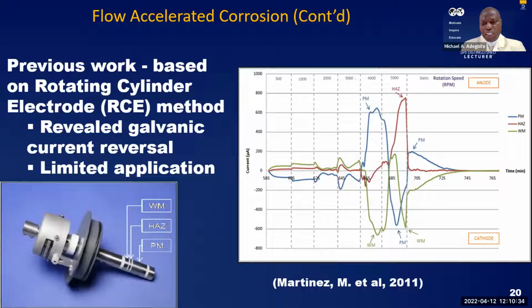In typical work that have been used to study the effect of inhibitors and to study preferential weld corrosion is this work by Martinez. Study the work, but because of the limitation of the speed or because of the limitation of the shear stress that could be generated, that could be simulated, this particular method falls short of it. But all is not just negative. A lot of lessons that we can learn from this work. And it is that it demonstrates that indeed inhibitors, chemical inhibitors, are inconsistent. They are not as efficacious as they have been assumed to be.